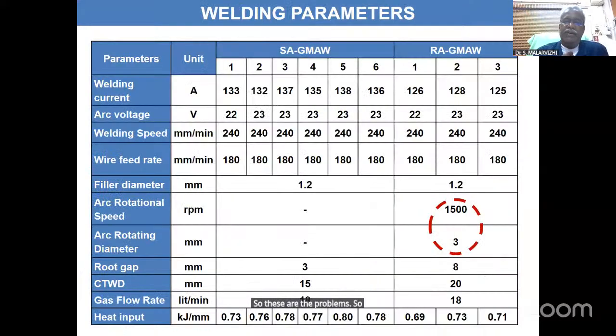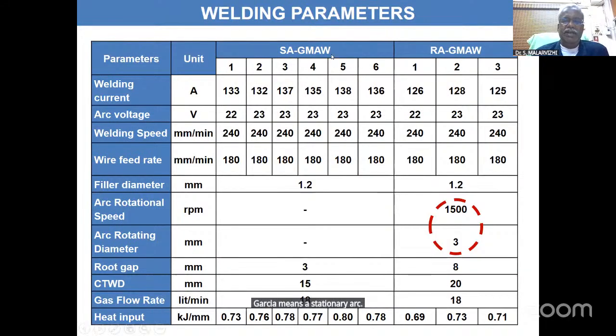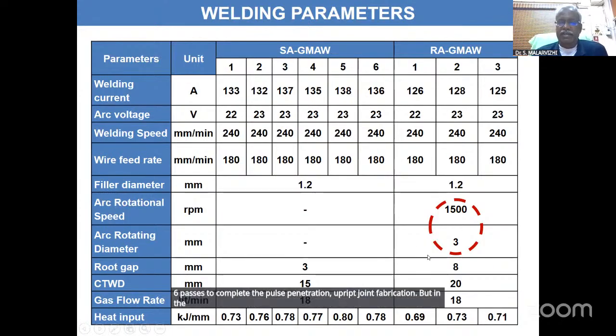So here we took the conventional MIG welding process, the GMAW process, referred to here as SA. SA means stationary arc, the conventional GMAW. REA is rotating arc GMAW, the new process. For 18 mm thickness plate, in the stationary arc we used 6 passes to complete the full penetration joint fabrication. But in the REA process, the rotating arc process, we need only 3 passes, because there is no edge preparation; it is a square butt joint configuration as welded here. That's why the number of passes is reduced.